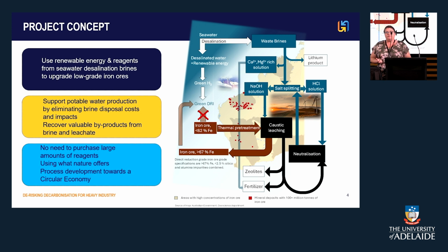We remove calcium and magnesium ions from the brine, and then we use a process called double membrane bipolar electrodialysis, or simply salt splitting. And that's how I will call it from now on. Salt splitting takes a brine, and through the clever use of membranes and an electric current, you separate your salt into a base, sodium hydroxide solution, and an acid, hydrochloric acid solution.